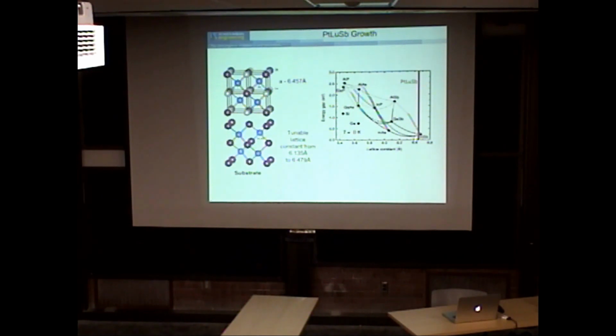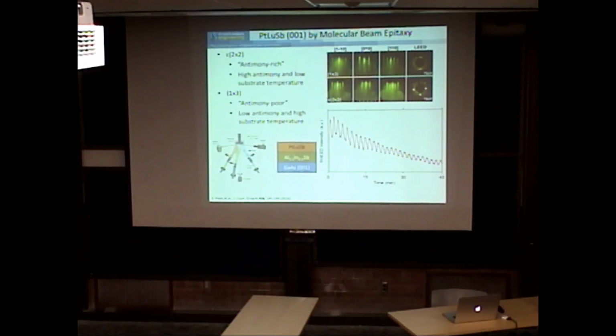So here now, just to show you the close match to indium antimonide. In fact, if we put a little bit of aluminum in, indium aluminum antimonide, we can perfectly lattice match to it. Okay, so can we grow it? Yes, we can. Same as we did the cobalt titanium antimony. We've grown it. It shows nice diffraction patterns, we get layer by layer growth. We get different surface reconstructions, and we've grown this on aluminum indium antimonide.